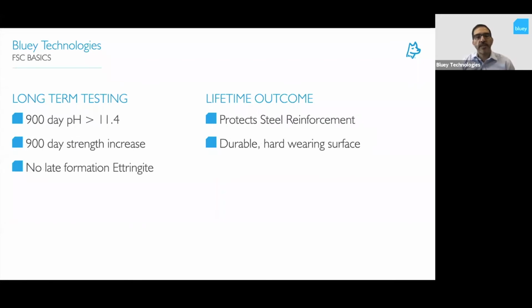On top of that, we've done long-term testing on pH. So we know that the alkalinity is maintained for more than 900 days. And we also know that we have a 900-day strength increase, and both of those things lead to protection of the reinforcement and a durable hard-wearing surface. On top of that, and finally, we know that we have no late formation ettringite, which can be a question around CSAs and needs to be tested for prior to delivery of the product.